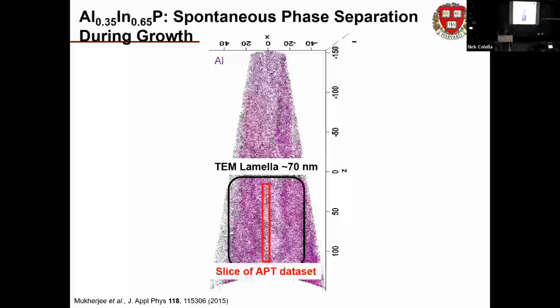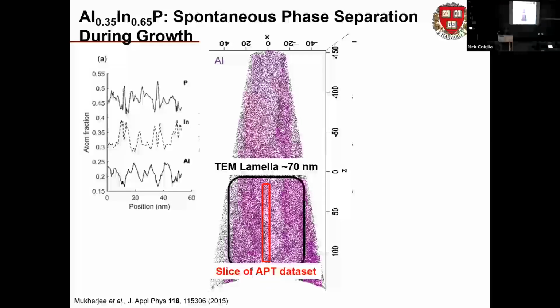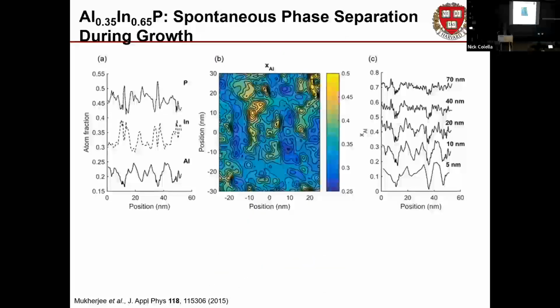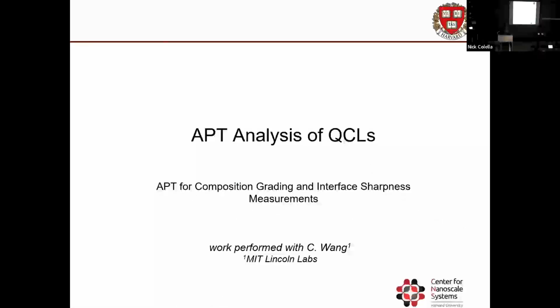But this is atom probe, and we can make slices of this data set however small we want, because it's a volumetric data set. So if we were to take a teeny little slice and look at the actual fluctuation of these compositions, hey, it turns out it matches up real nice with the optical data. In fact, we can even plot it in 2 dimensions and see, again, a little topographic plot of the ratio between aluminum and indium, and we can see that we got composition fluctuations over like a 5 nanometer length scale, and fluctuations of 25% in composition, which is a ridiculously big difference. That was all very interesting and fun, and not what these folks wanted to see, but hey, we found out what their problem was. Okay, so that's sort of composition of a bulk piece of material.